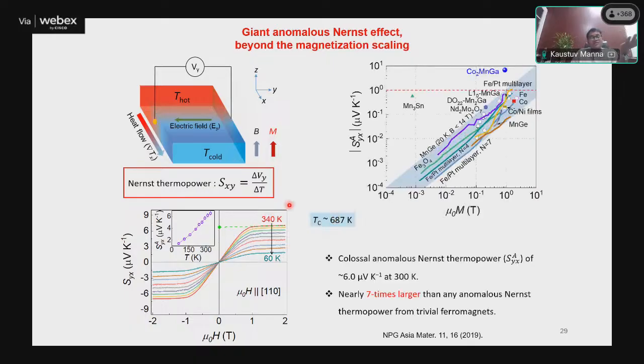And if you have anomalous Hall in electrical transport, then obviously you can do thermal transport also. Thermal transport means you can create a temperature gradient. I think Shubhajit already gave a detailed talk on this, what it represents. So if you have a compound with a Weyl semimetal where the band crossing is very close to the Fermi energy, like in this case cobalt 2 manganese gallium, we have observed that the Nernst coefficient, the Nernst thermopower, is very high. This is in log scale. It is a few times larger than any compound ever reported in the literature. So you can get such exotic properties.